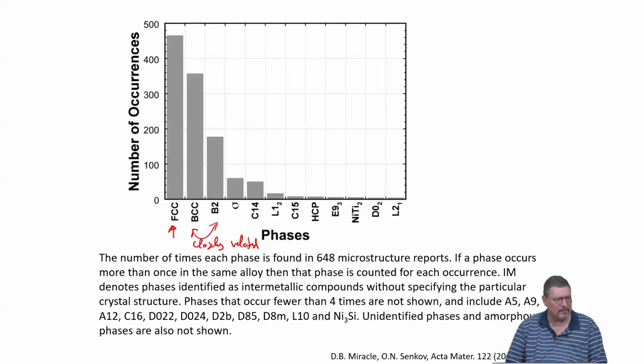The sigma phase obviously occurs often, but you see it occurring often because it will form at the lower temperatures in many of these FCC high entropy materials. And these more complex structures are very rare, and often they also form as precipitates in given high entropy systems when they are held at lower temperatures, so that they go from single phase to two phase or more multi-phase structures, especially decoration of grain boundaries, of triple junctions, and so on.